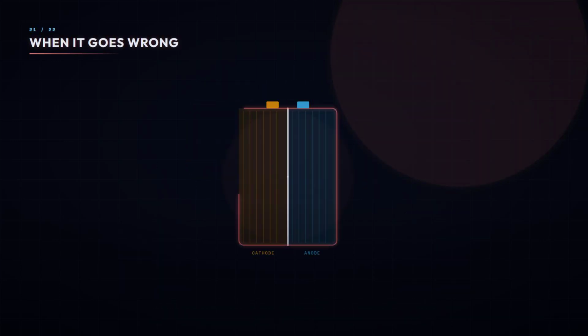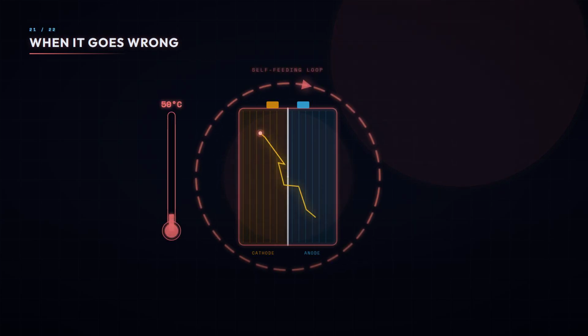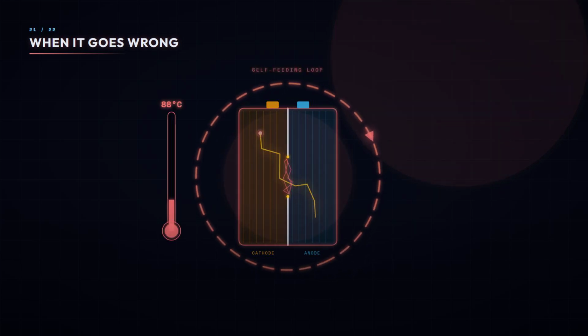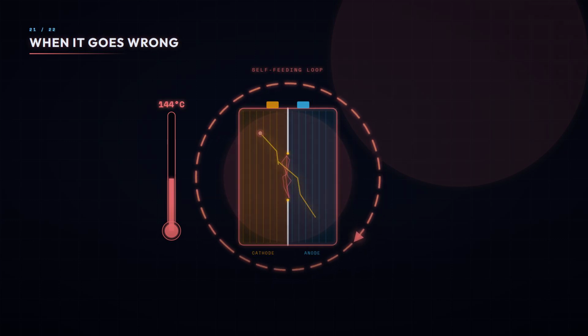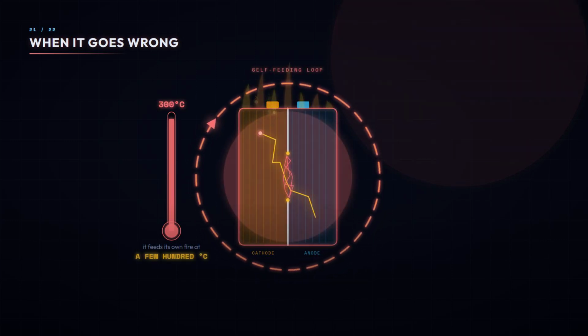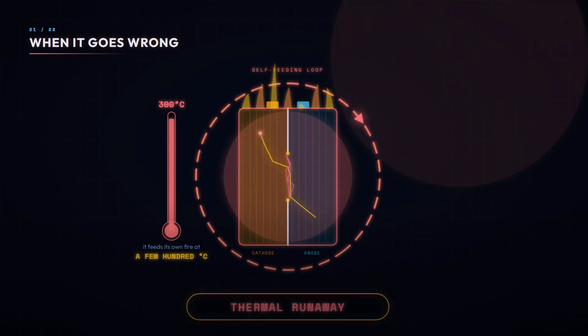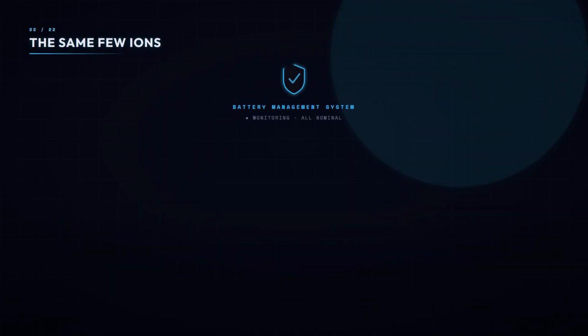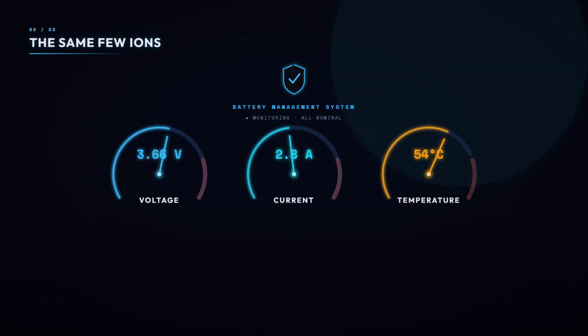And when it does go wrong, a short or severe overheating starts a feedback loop. The separator melts, electrodes react directly, the cathode releases oxygen, and at a few hundred degrees it feeds its own fire. That's thermal runaway, and guarding against it is everything. Yet most cells are remarkably safe because a management system watches voltage, current, and temperature and shuts things down early.